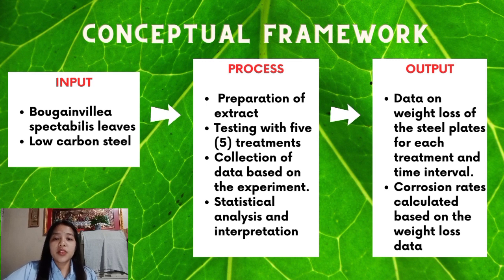The square-shaped low-carbon steel plate specimens, with a size of 1 inch by 1 inch by 1.8 millimeters, were submerged. But prior to submersion, the specimens were subjected to cleaning and initial weighing before the weight loss analysis and corrosion rate. There were 5 treatments, including 3 different concentrations of Bougainvillea spectabilis leaf extract, which are 30, 20, and 10, and the other 2 treatments are the positive control, the commercially available corrosion inhibitor, which is 84 ml of Turco rust converter, and the negative control, for which the researchers used 85 ml of 1 molar hydrochloric acid solution.